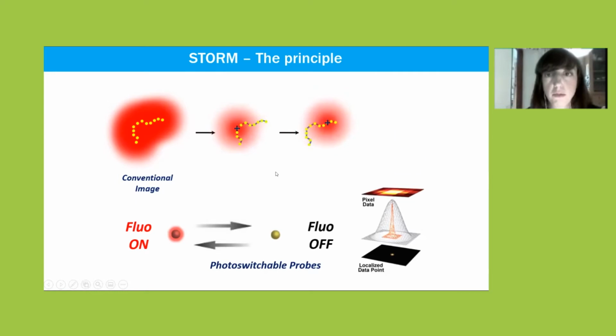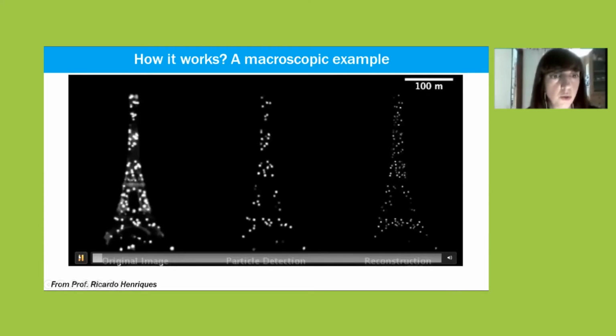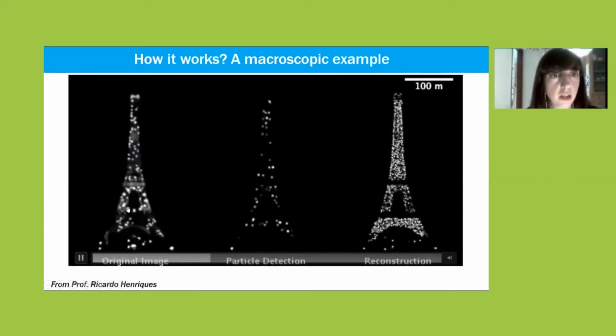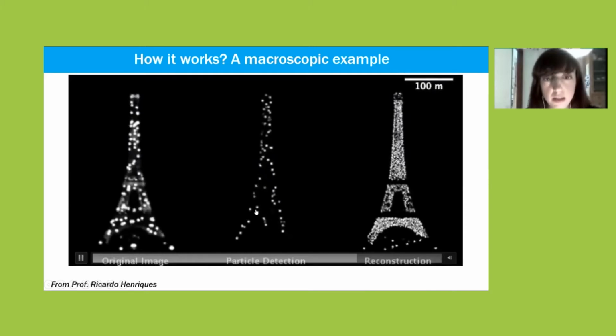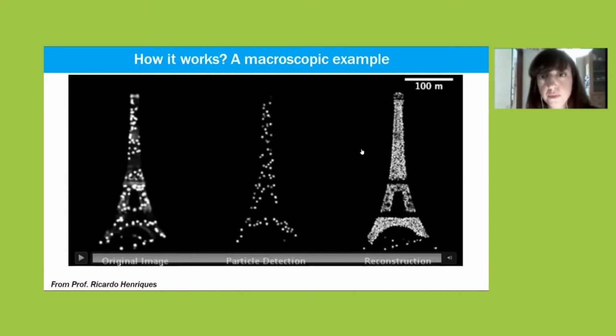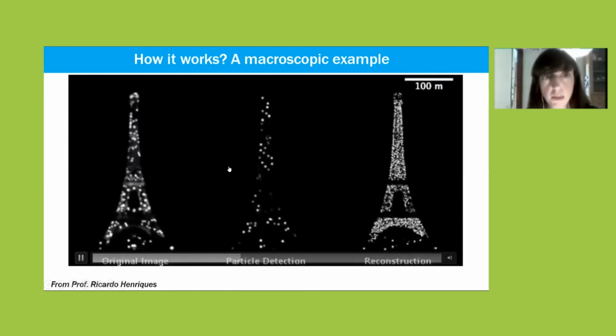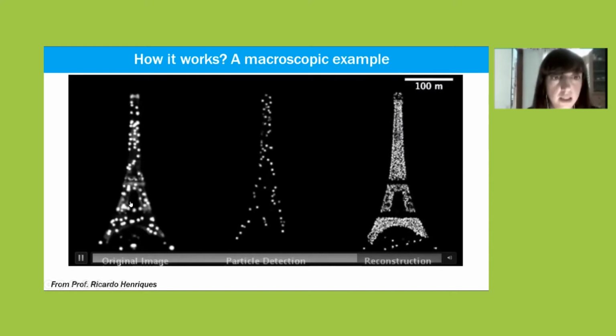So you do this typically for many, many frames, 20,000 frames, 50,000 frames. And at the end, that's why I was telling you that it's a very long acquisition. It takes minutes to get all these images. So at the end, you add up all these points and get the reconstructed image. Okay, so it works like this. So it's like the blinking of the Eiffel Tower. Each of these blinks you detect, and then you add these points at the end in the reconstructed image. So you need fluorophores in the places you want to image to get the final structure at the end. Like here the antenna that is not labeled, you will not see it at the end.